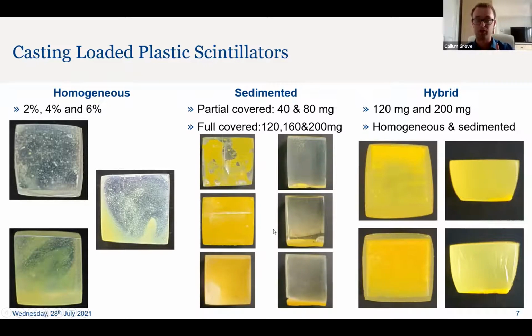And so we decided to have a highly concentrated sedimented layer at the edge of the sample instead, so that we'd have a very highly altered effective Z in this quantum dot region. And so we did two versions of this. We had a fully sedimented one, as you can see here, which is more or less a clear plastic with quantum dots at the bottom. There's a few quantum dots that had settled throughout the bulk medium on this scintillator here. But generally, the idea was to have it all coalescing at the bottom.